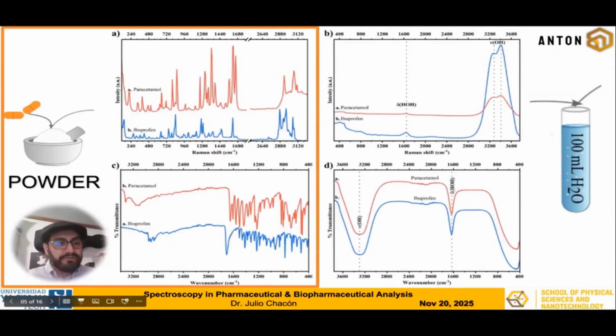In order to start, first of all, we need to understand that pharmaceuticals like paracetamol and ibuprofen can be measured in a raw powder by using Raman spectroscopy. It's a very straightforward, simple measurement where you simply put some powder below your Raman spectrometer, then you make the measurement, and you immediately obtain the fingerprint of this paracetamol or ibuprofen. That's normal, it's standard. And you get a spectra that is similar to the one that I'm showing you here, with all the vibrations that correspond to the different molecular sections that the whole molecule has.